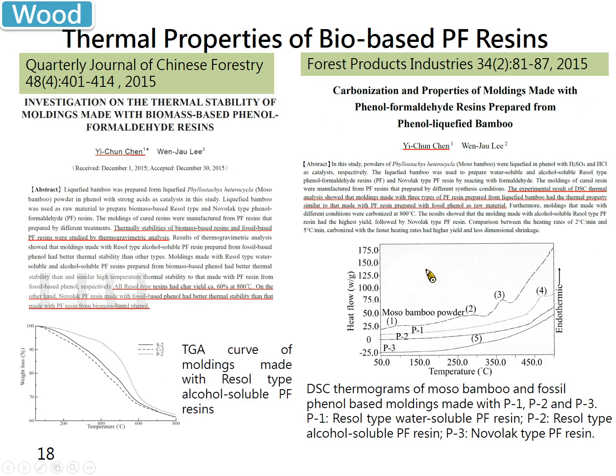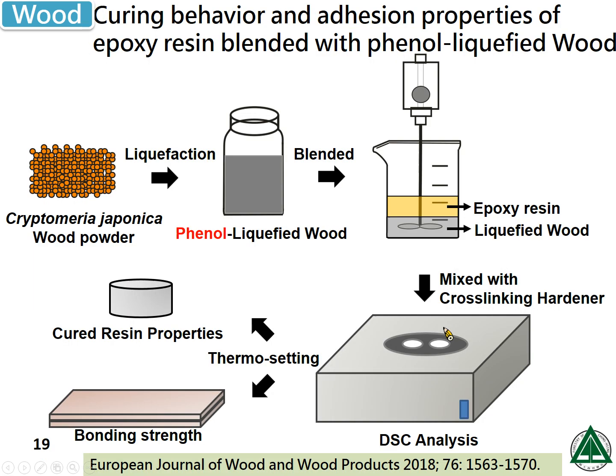The bio-based molding also shows pretty good thermal stability. I think it's better than wood and some traditional ones. It's similar to traditional PF resins. We also think about what kind of application we can use. The epoxy resin is a high-cost product, so we try to mix it with liquefied wood. Results show liquefied wood can replace epoxy resin, which has really good curing property and bonding strength.